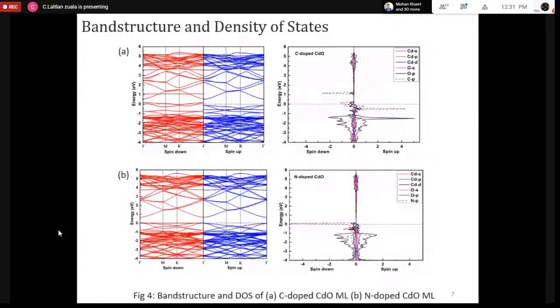You can see from here that carbon and nitrogen doping also exhibit half metallic behavior when a carbon atom or nitrogen atom is put in place of the oxygen atom. But in the case of nitrogen and carbon doping, the band gap remains almost the same as the pristine structure. The noticeable difference in the band gap in B doped in comparison with the pristine structure is attributed to the shorter bond length of the extrinsic B atom. Now, next slide.